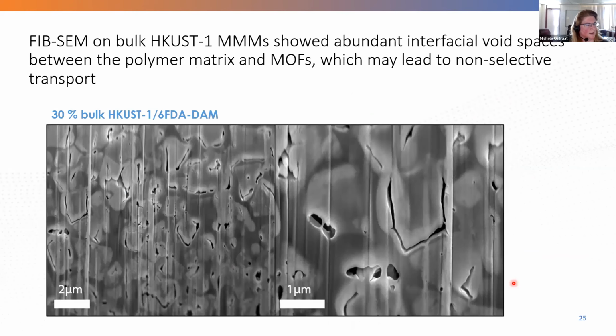When you do a FIB-SEM on these, you notice for the bulk materials, a lot of voids. This is not a good thing for membranes that are based upon a solution diffusion model. And it leads to a lot of non-selective transport. So basically, any material is able to flow through those voids. So your membrane is just not selectively separating anything.